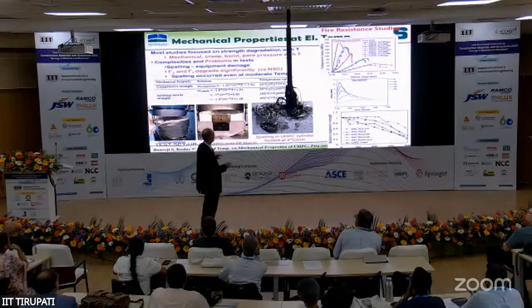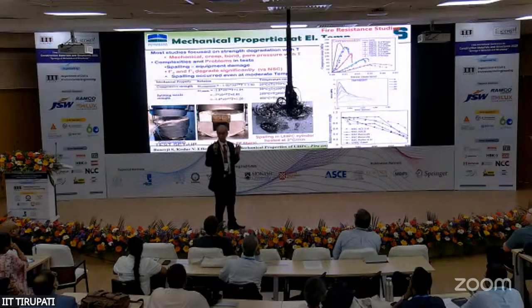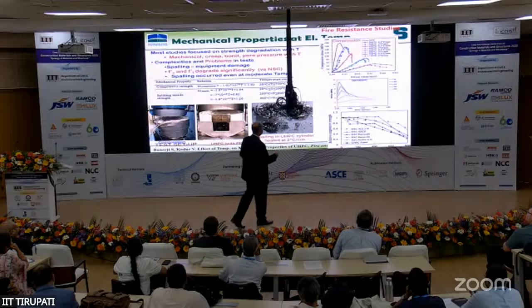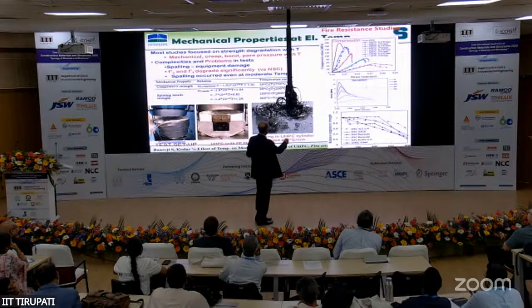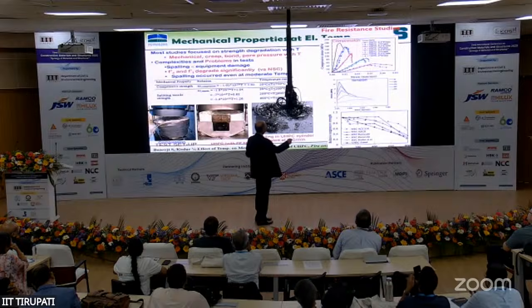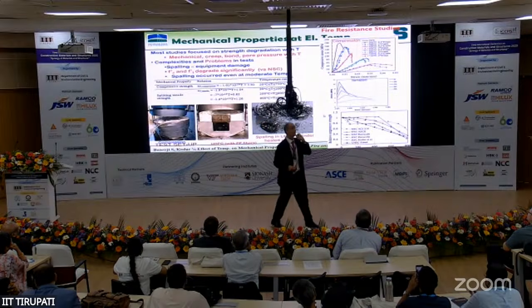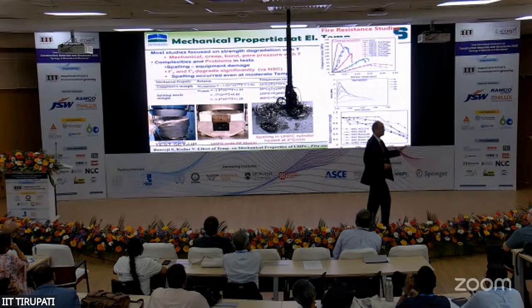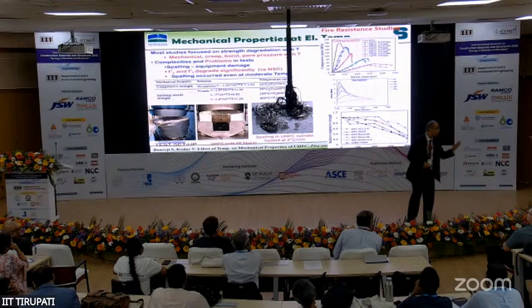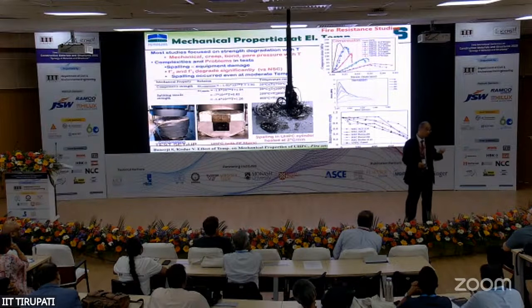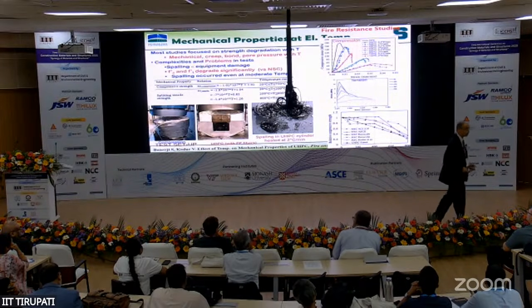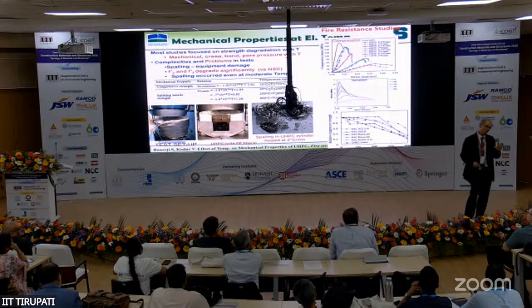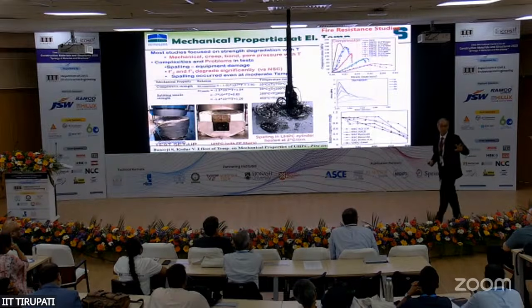similarly specific heat. When it comes to compression stress strain curves, you can see this at room temperature, 200 degrees, 400, 600, 800, 1000 degrees centigrade, but the rate of heating is different. So that's why, when it comes to guidelines, if you are using UHPC in an office building, it's okay. But if you are using it in a parking garage where cars can catch fire, if you are using it in a bridge, if you are using it in a tunnel, you have to do something. I mean, it's dangerous.